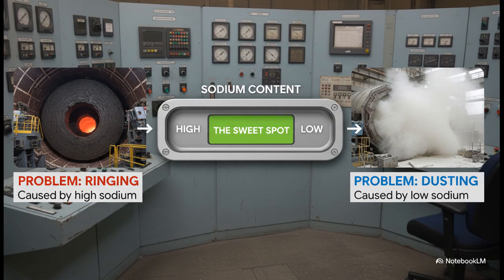See, high sodium makes everything sticky, and you get rings. So the obvious solution is to wash the mud better, get the sodium down. But if you go too low on the sodium, the lime particles don't clump together like they're supposed to. They don't nodulize. Instead, the whole kiln just fills with fine dust. So you're constantly walking this tightrope, trying to find that perfect sweet spot between ringing and dusting.